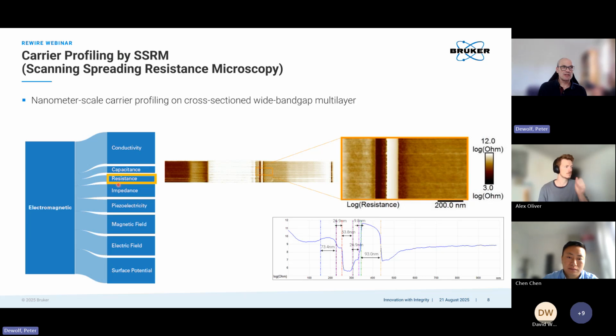Similar to conductivity, resistance typically is considered a different property, mainly because resistance, when we go to semiconductors, will vary over many orders of magnitude depending on the carrier level or dopant level within that semiconductor. This is a cross-section device. I don't show the topography because it's pretty boring, it's not showing anything. The sample is prepared by cleaving.